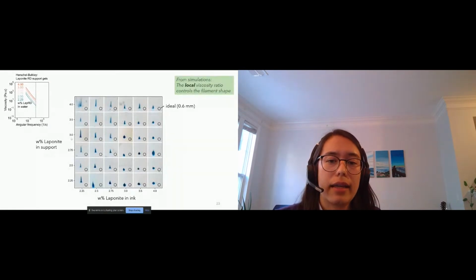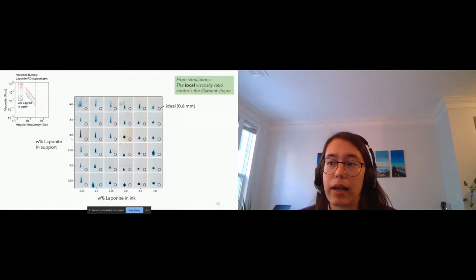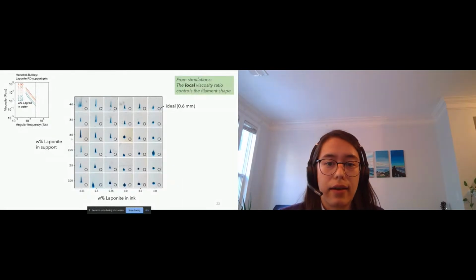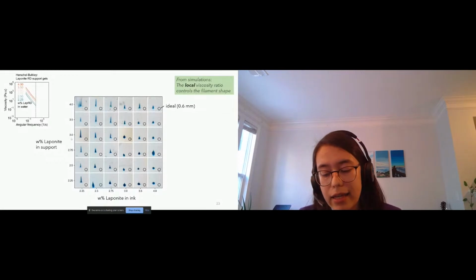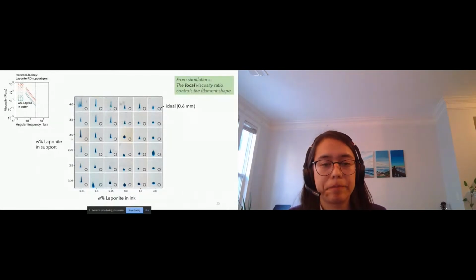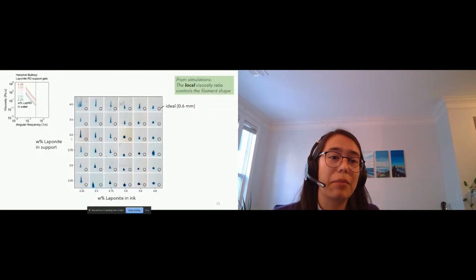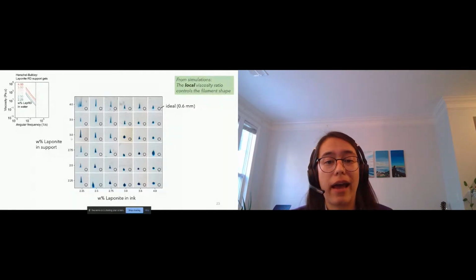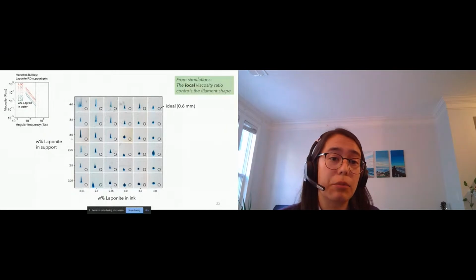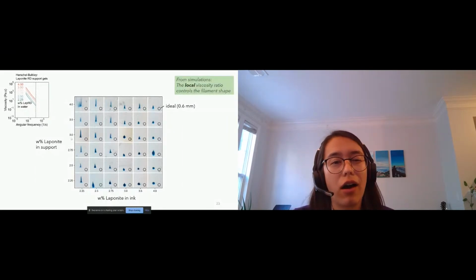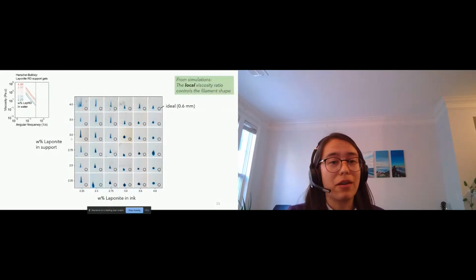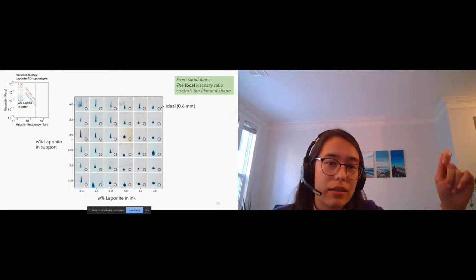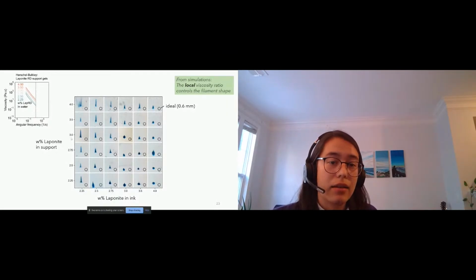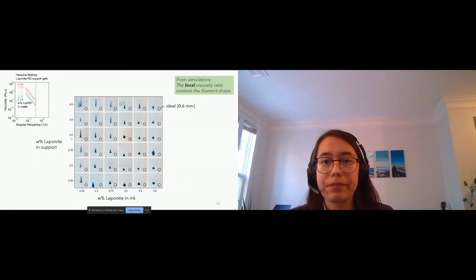So if you look at the bottom right corner of this plot, you can see that as we go to high ink viscosities and low support viscosities, we get circular filaments. If we go towards the top left corner of this plot, where we have low ink viscosities and high support viscosities, we get very tall and narrow filaments. And these filaments also get sort of sharp edges at the top and at the bottom of the sides.